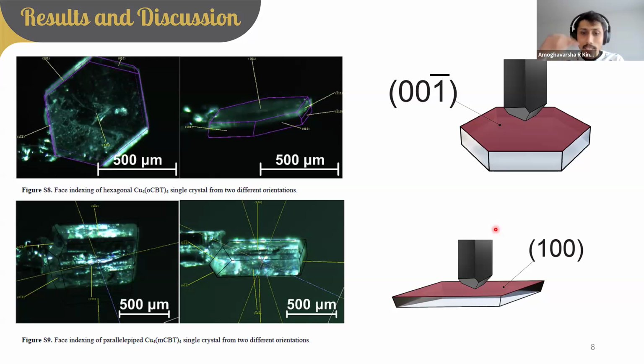So if we can indent the sample and study only that point of indentation, because the indentation is occurring in the nanometer range, only that point should be focused to understand the change in photoluminescence. If you get some background photoluminescence from the regions which are not indented, then it will not give us any changes compared to the normal measurements. So precise measurements are very much required to understand that.